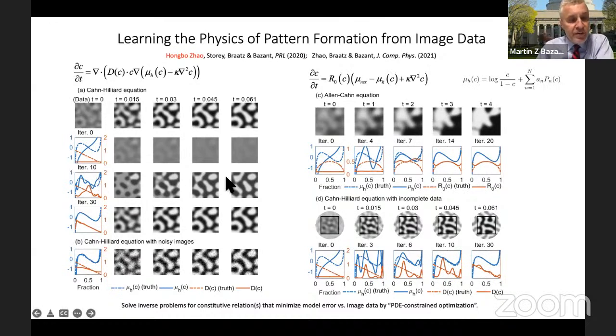And what you can see in the subsequent rows is that, after only 10 iterations in the second row and 30 in the next row, we can basically get simulations that look indistinguishable from the truth, which is the top row, using only 5 snapshots of the dynamics in this case. And both the blue and the red curves, the chemical potential and the diffusivity, have been learned with high accuracy, at least over the range of concentrations that are in the simulation in the middle. In fact, as shown in the lower row, we can also add noise to the data and still learn those functions quite accurately in this case.